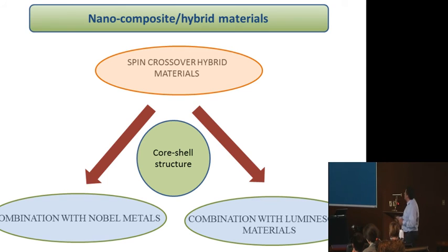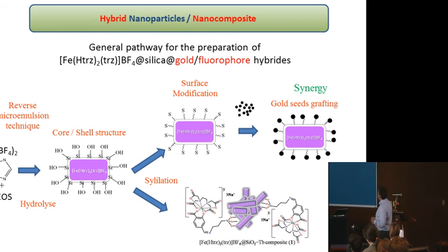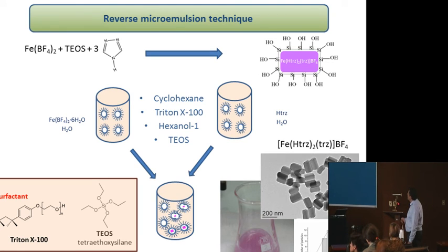So we developed a platform with core-shell nanostructures. This is a general pathway of this strategy, but I want to come back to different steps. Here we use the reverse micelle technique with a different surfactant, in this case Triton X-100. The strategy is to add the precursor for the spin crossover nanoparticles, but also the precursor, TEOS, tetraethoxysilane, for the formation of the silica shell. So you have all the reactants for the growth of the spin crossover nanoparticles, and the idea was to have at the same time a shell of silica around. Here we can see the result, the TEM.